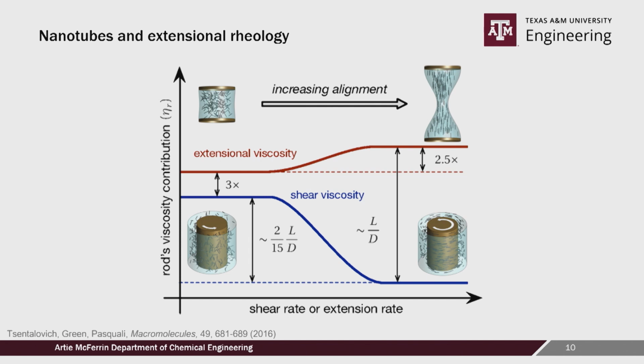And what's interesting is using kinetic theory, you can say, if I have a suspension of Brownian rods, can I predict the behavior, the shear rate dependence of the shear viscosity and the extensional viscosity? How does that relate to the length of the nanotubes? You can come up with equations that actually show, if you make the nanotubes longer, here's how that will impact their extensional viscosity behavior. And if you have that equation, then that means you can actually measure nanotube length with your rheometer.